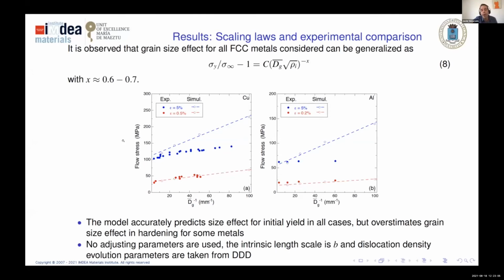Okay, and with this model, can we reproduce laws from experiments? So we have compared with a set of experiments by different people in different materials. Now I'm showing only copper and aluminum, and we are checking our simulations for the yield, so very low strain, and large strain. We see that we're able to predict the size effect very accurately for the yield or near the yield, but sometimes, depending on the metal, especially in copper, not too much in aluminum, we overestimate the size effect at larger strain. So in the case of 5%, so it's the flow.